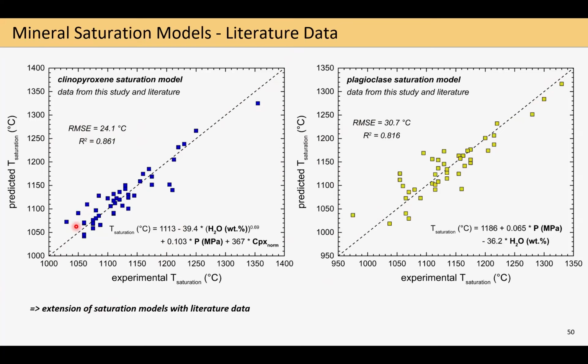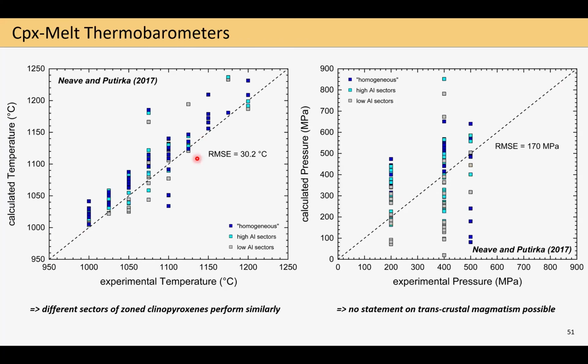And before I now come to the end, I first want to show you what we can also use this entire data set of my experiments for. Namely, we can, for example, use it to test the general performance of some thermobarometric algorithms and their general applicability to natural, or especially now mafic calc-alkaline, rocks. And here I want to shortly focus just on the hot topic of clinopyroxene-melt thermobarometry, where what I did here is that I took my experimental melt and clinopyroxene compositions and then used them to calculate, with all these models, the predicted temperature and pressure of crystallization. And by comparing them, of course, to the measured and known experimental conditions, I can judge a little bit how well these models are working.